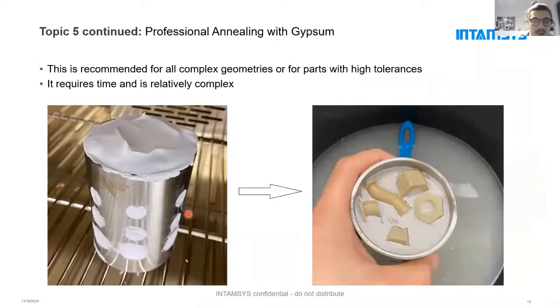One thing about annealing is definitely how to do annealing. And I have only one short slide for you. I could speak 2 hours about annealing, but what we mostly do, especially for sensitive structures, is to put the part in gypsum. So you mix up a gypsum slurry, put all parts within gypsum in a special container, dry this container, then heat it up first to 120, 150 degrees, then you heat it up to 200 degrees, then you cool it down to 150 degrees, then you naturally cool it down to room temperature, and then you wash